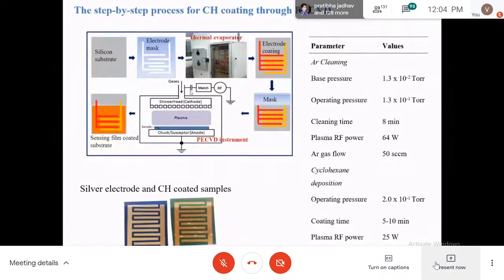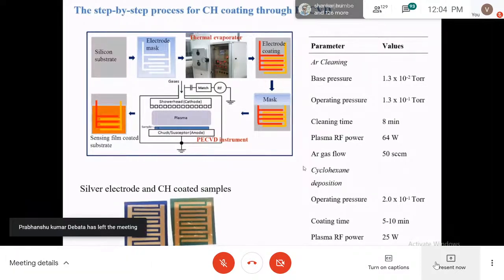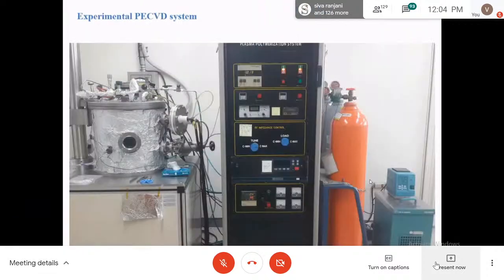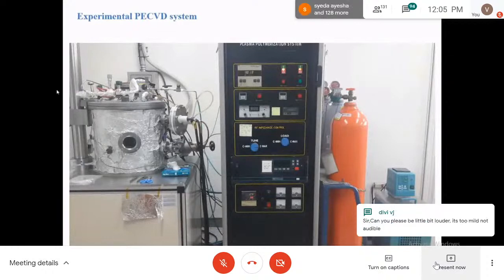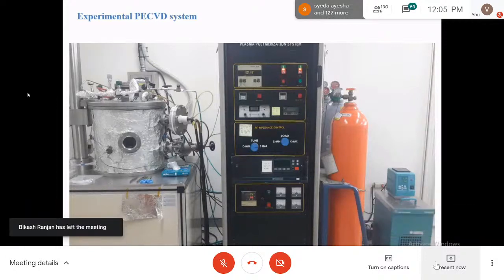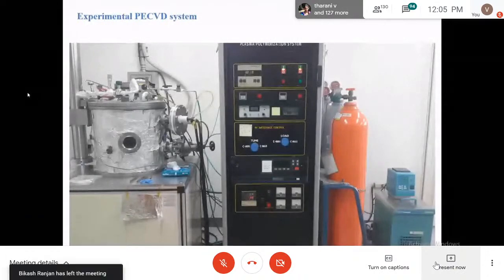Then we use this PECVD, plasma enhanced chemical vapor deposition instrument, because we use the cyclohexane as the source for polymer material. This cyclohexane monomer is transferred to the PECVD apparatus, where it is ionized, and then it is deposited on this electrode substrate, this sensor substrate, and then we get the sensor material like this. This is the actual deposition tool. Inside we keep our sensor substrate, and cyclohexane is transferred by thermal heating, and then it is taken by the hydrogen carrier gases.